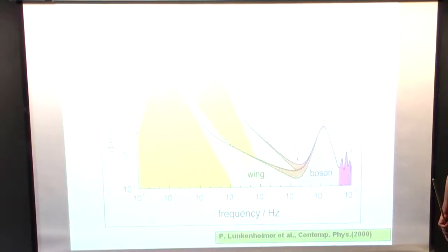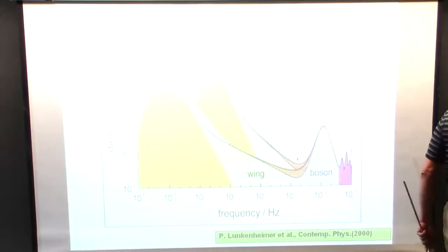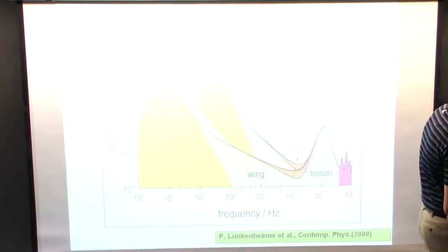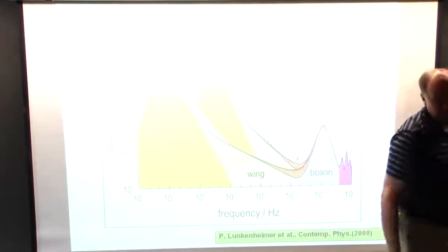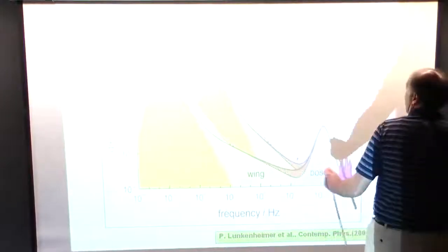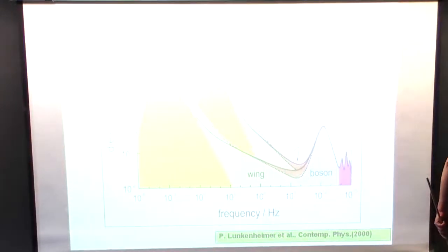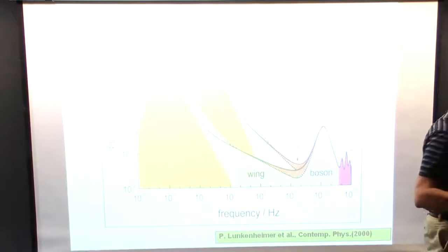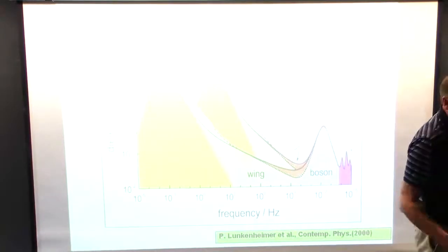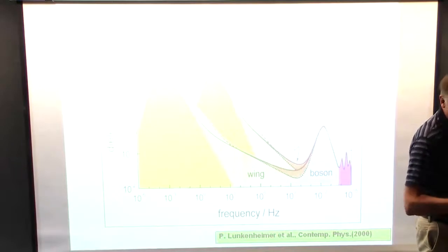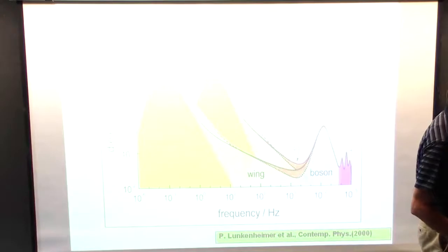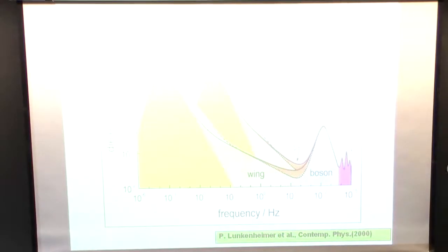And then you can talk about Tg. This is 1 over Tg, somewhere at some certain arbitrary number. And the mode coupling temperature is actually around the merging temperature. And then there are people in the material science department who talk about crystallization noses, where this happens. And that's it. So I'm talking here about this region or below, where you clearly see the landscape already by forming certain configurations in the liquid, polyeders, clusters, superclusters maybe even, and the metallic glasses, by the way, are in between here somehow.